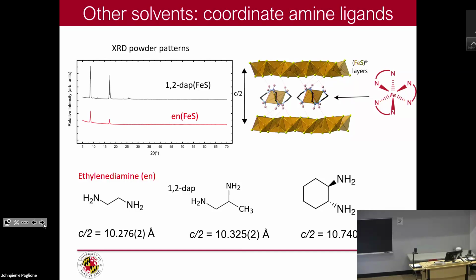Just be aware that all of these solvents have hydrogen bonding in them, and so they love water too, so they'll soak up water. And so you always have a little bit of water in your system, unless you work really hard to get rid of the water, like you work in a glove box, you order ultra dry solvent or something like that. Otherwise, you can always count on some water being in there, which isn't a terrible thing, because sometimes water is a little bit like a catalyst in these materials and helps with crystal growth.